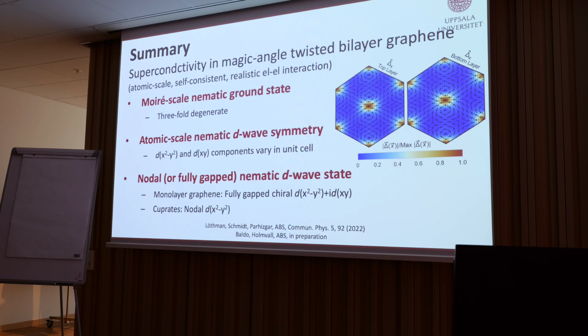So I spontaneously break rotational symmetry in the superconducting state. I don't need to break it in the normal state first. But I also get an atomic scale nematic D-wave symmetry. So I have nematicity on the two length scales in the system. This state is most often nodal, but it can be fully gapped.